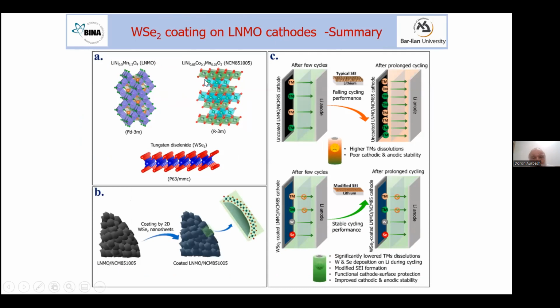So we have a situation where we have a buffer zone on the positive, and we also have an effect of the layered compound on the lithium negative, and in such a way we have stabilization on both the lithium and the cathode material. We avoid the detrimental dissolution of transition metal from the cathode to the solution, and then their deposition on the negative electrode, and in such a way we demonstrate impressive stabilization.